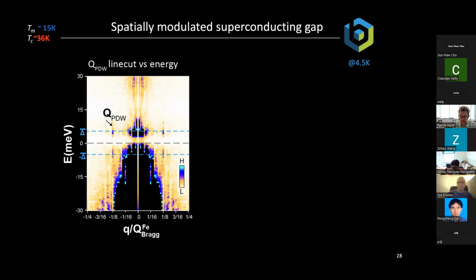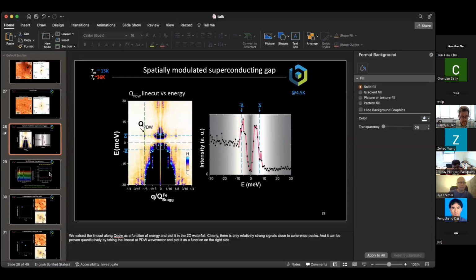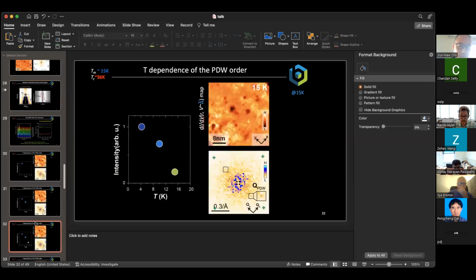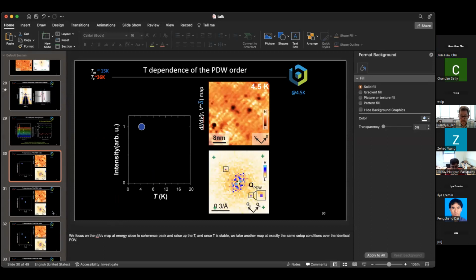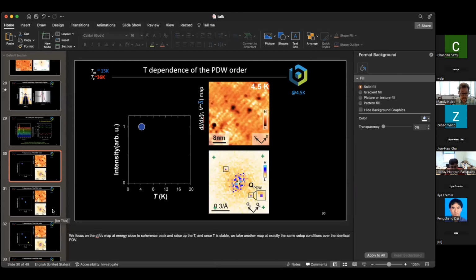Thank you. Yeah, Junhao. So, very, very interesting results. Do you see a temperature dependence of the modulation wave vector Q? I mean, supposedly the Q is set by the exchange, and then it should go down as you get close to the magnetic transition temperature. Yeah, very good. So far we've looked for that, and we have no evidence so far for the change of Q. So you're absolutely right.